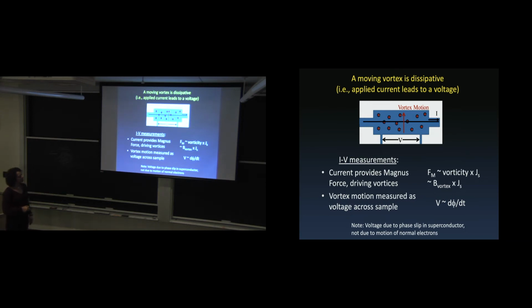The vortex crosses the sample, and because it basically acts as a phase slip, you get a phase slip across a superconductor, which produces a voltage, right? You change a phase across a superconductor, you get a voltage, and that's what leads to an applied current giving you a voltage. That's what you measure as a resistance. Just to be clear, it's not the normal electrons in the vortex core that leads to resistance. It's really driving this thing and getting this phase slip, which leads to a resistive state. But it is still dissipative. You get resistance when you measure this in a superconductor.